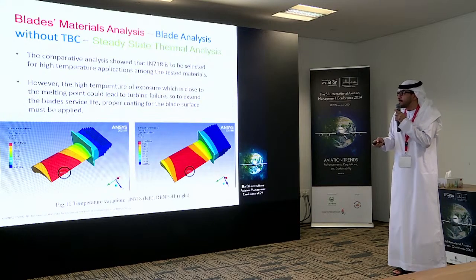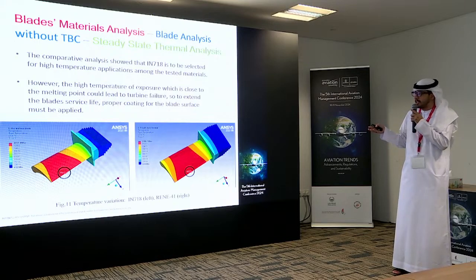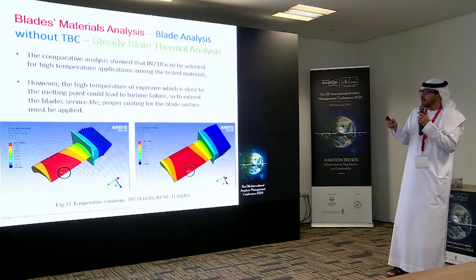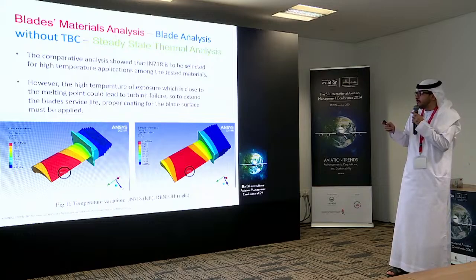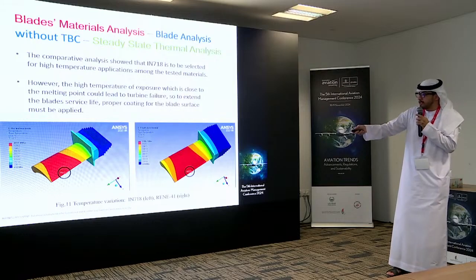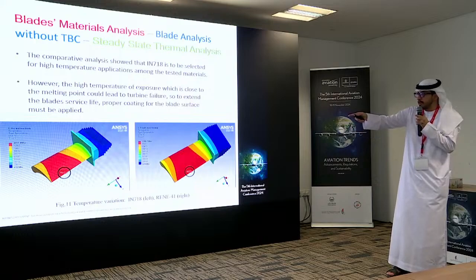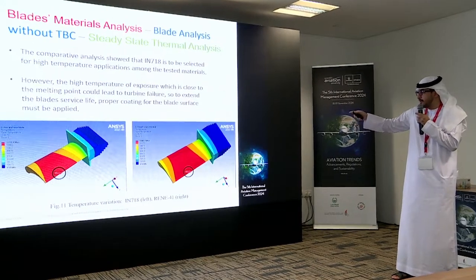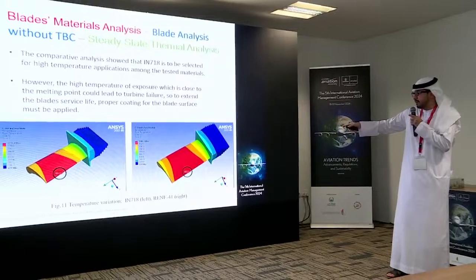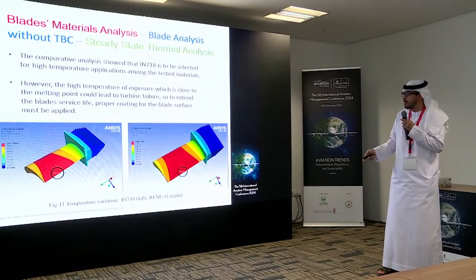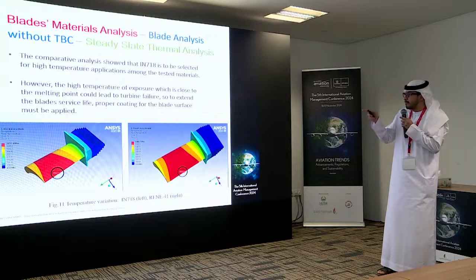Now for the steady-state thermal analysis. After the static analysis, we have the thermal analysis. The comparative analysis showed that IN718 is to be selected for high temperature applications among the tested materials. You can notice in figure 11, on the left side, you have the Inconel 718. The highest temperature that was captured was 1,155. On the other hand, you have the RENE41 at 1,186. However, the high temperature of the exposure, which is so close to the melting point, could lead to turbine failure. So to extend the blade's service life, a proper coating for the blade surface must be applied.